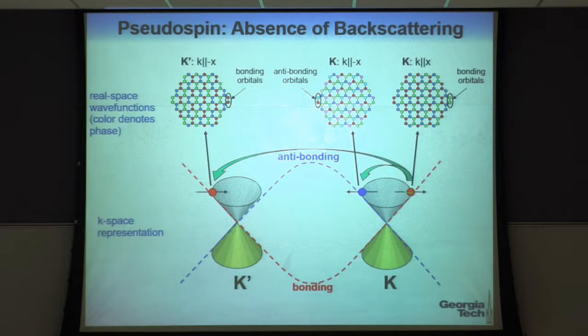So this scattering from here to there, which is a small wave vector that would correspond to scattering from something that is physically a fairly large size, it actually can't be done because I would have to flip the pseudospin. Physically, what that means is I would have to take bonding type orbitals and dump them into an anti-bonding configuration, and that's just really hard to do. You can do it if you have a large wave vector, which is something that's determined by small structure things, so you can transfer lots of momentum. In that case, I can get a scattering all the way across the Brillouin zone of the material, and I can get some backscattering in that case, but only if I have structures that are on the atomic scale. They're the only ones that can provide that large momentum transfer.